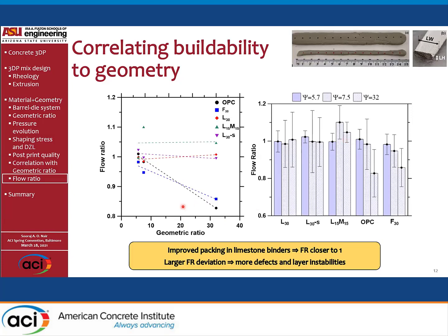This shows that the higher requirement for steady state pressure is restricting the mixture to flow, and there is a lot of liquid filtration, so the particle packing will also be much lower. So your effective area in the post-print output will be much lesser.